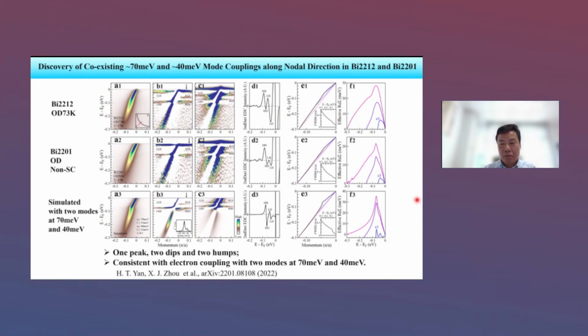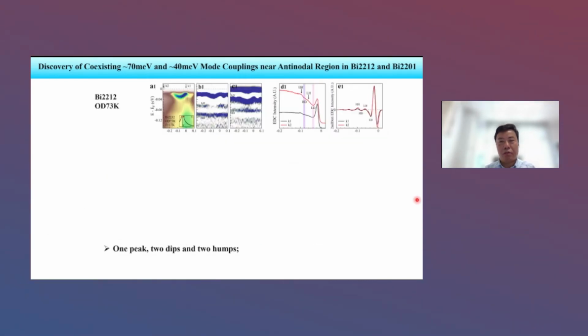Okay. Then if we move on to the antinodal region, in this case the band bottom is smaller than the phonon energy. Here, the phonon energy is larger than the band bottom. Usually the usual kink method cannot work because it doesn't cross the band. But using our method, the second derivative, you can still see two flat bands here. Okay, that means two mode couplings here.